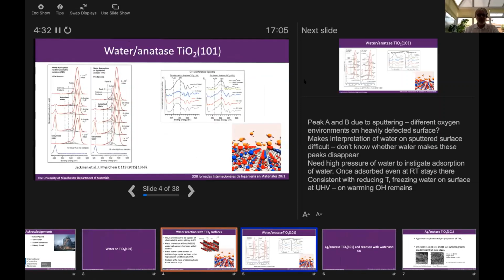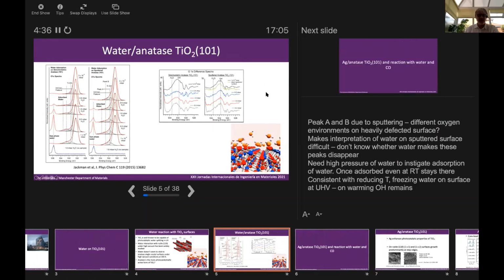So when we got our new ambient pressure XPS instrument in Manchester, I'm hoping that Claudia has given an introduction to photoelectron spectroscopy. So normally we're working in photoelectron spectroscopy in low pressures, so 10 to the minus 8 to 10 to the minus 10 millibar of pressure. But this new instrument essentially uses pumping along the lens system, which allows us to measure at much higher pressures. We still can't get to atmospheric pressure, obviously, but we can now get to pressures certainly of around 6 millibar or even up to 20 millibar and still get reasonable information.